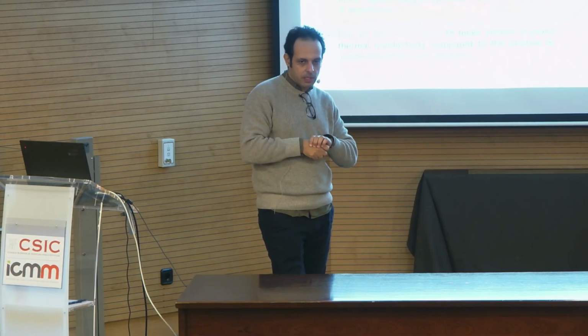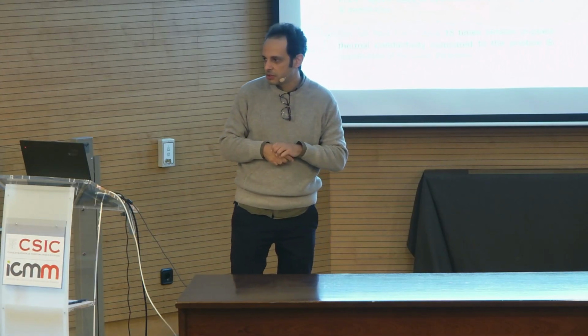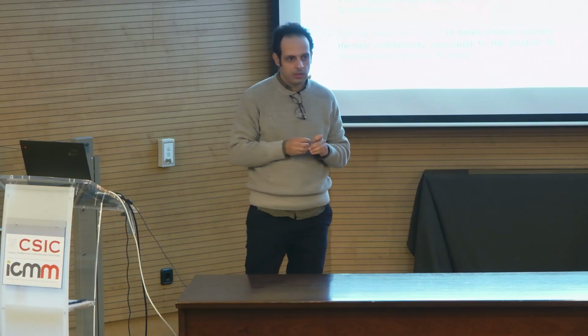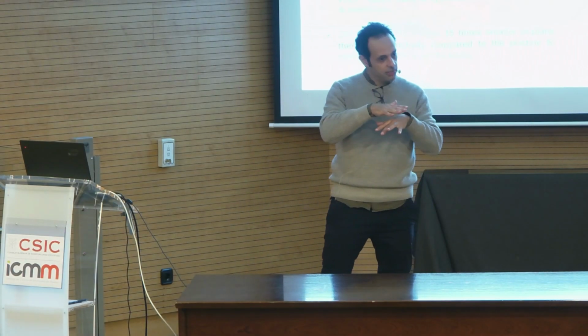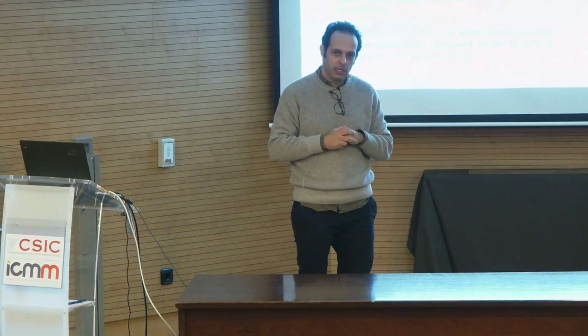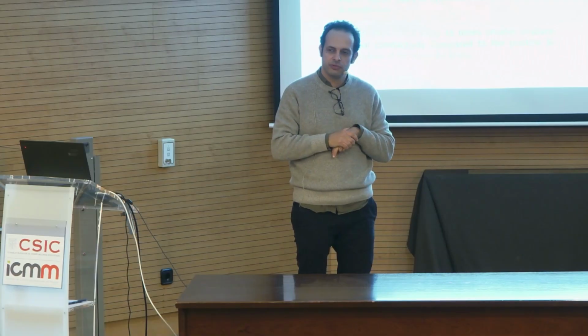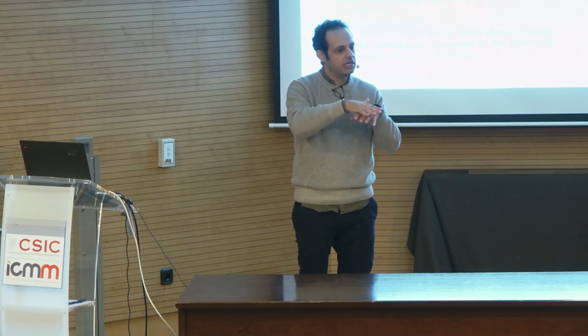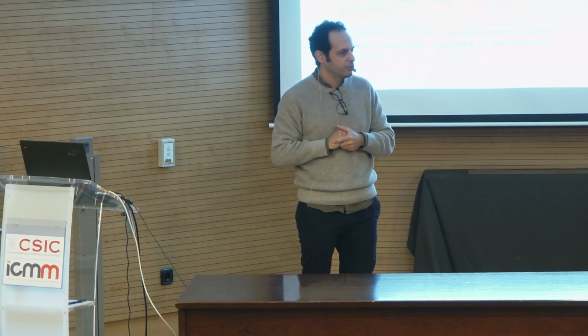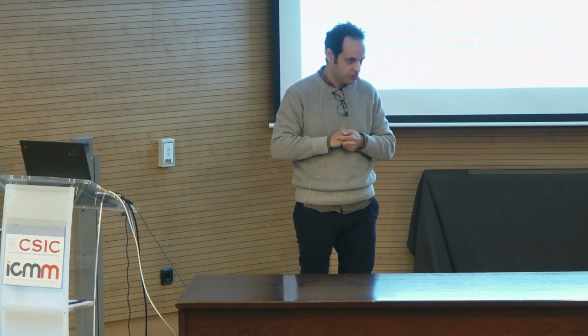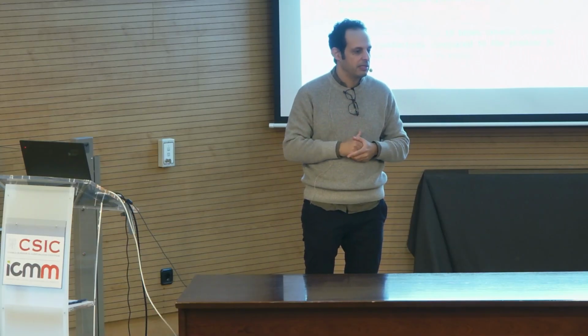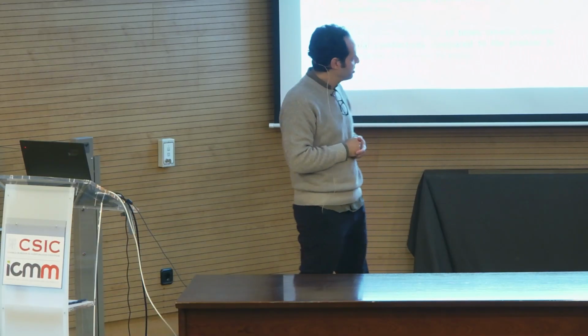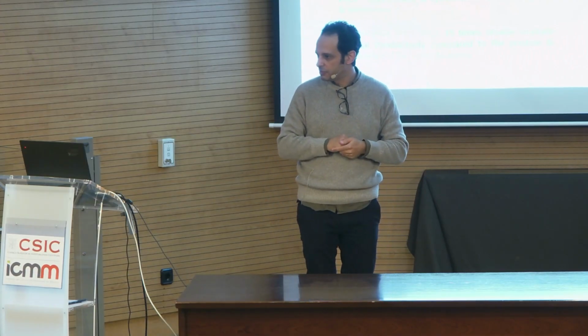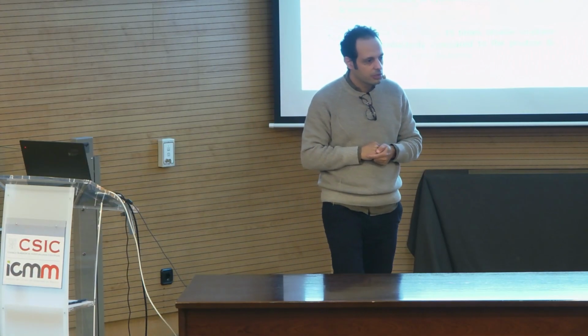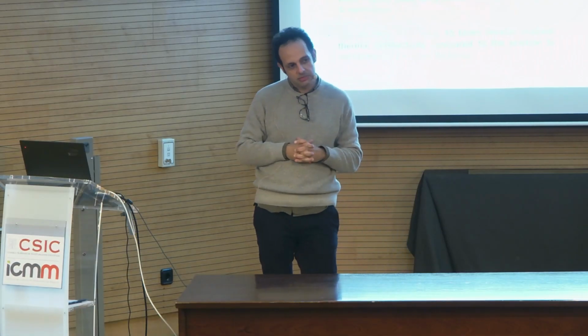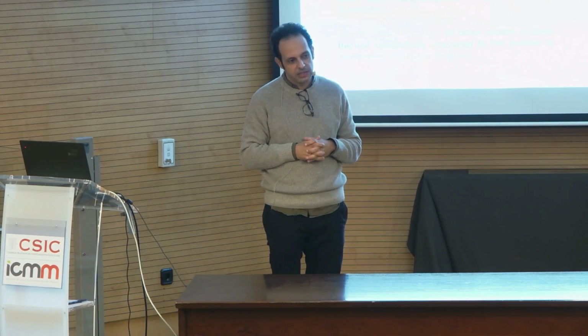Actually, there is a very nice work published, I think in Nature, two years ago or more, where they did what you were saying, exfoliating molybdenum disulfide atomic layers and stacking them at different angles, and they managed to get very high thermal resistance. And actually the values that we got are very close to these values, and the ones that we published. So yes, this is another way which is very interesting. It's already done.